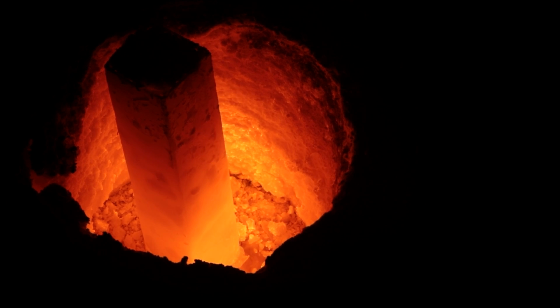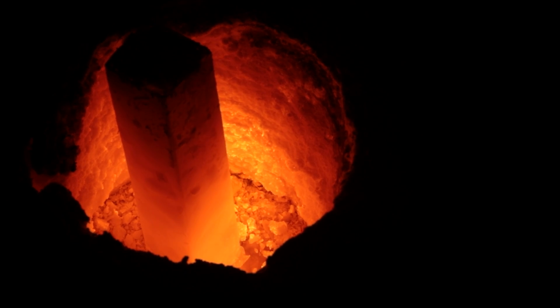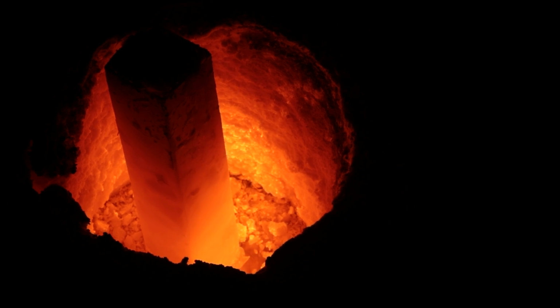And it's going to be getting that carbon from the charcoal and the sodium carbonate, but it's not directly diffusing it. What's actually happening is, at these high temperatures with little oxygen, they both start to break down to produce carbon monoxide gas. The carbon atom will then split off and diffuse into the steel, and the spare oxygen will bind to create carbon dioxide.